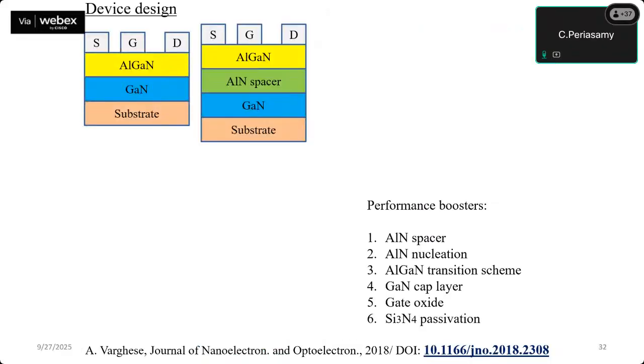And also we have used that gallium nitride cap layer, which will reduce the traps at the surface. There may be different traps present in the aluminum gallium nitride surface. So if you introduce a gallium nitride cap layer above the aluminum gallium nitride, that will reduce the different types of traps present on the aluminum gallium nitride surface.